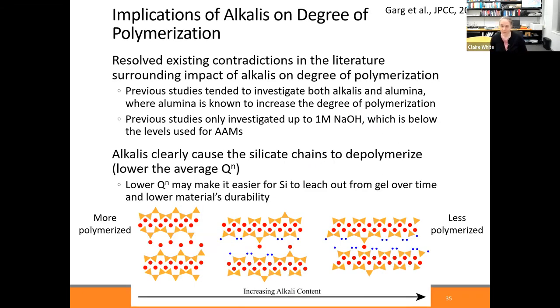I've essentially said this already, but it's the degree of polymerization that's very important. And so what we found was that as you add sodium to the system, alkalis, it causes the silicate chains to depolymerize. This might be of a concern because the lower coordinated these silicate units are with each other, it's likely easier for the silica to dissolve over time in aggressive environments. But on the flip side, we know that aluminium increases this degree of polymerization, makes it more polymerized. And so that's a good addition to have if you're going to have sodium coming at the same time, which means when you're making concrete, if you're trying to reduce the amount of Portland cement powder and you're using something that has sodium in it, you also want it to have reactive alumina in there as well.